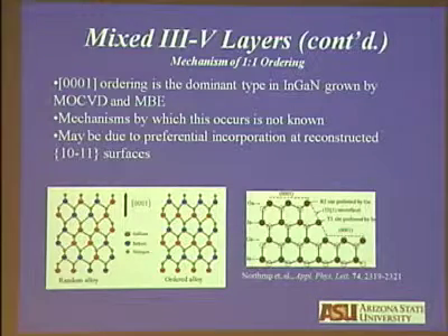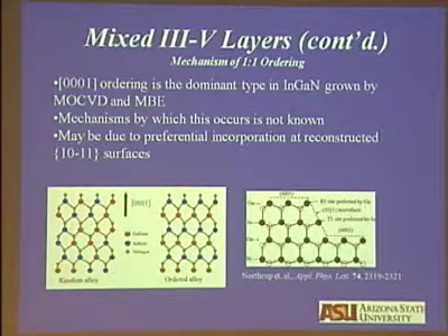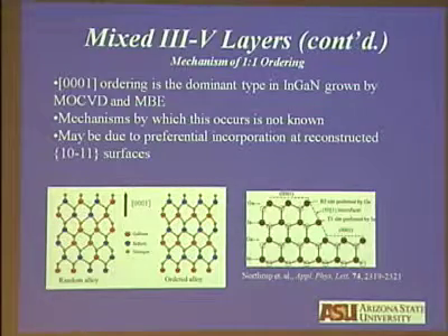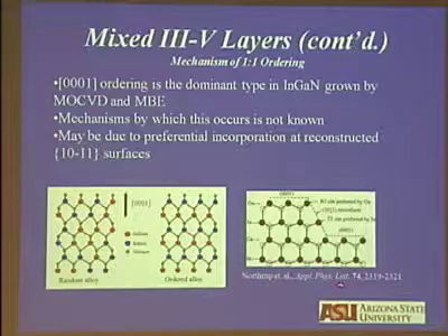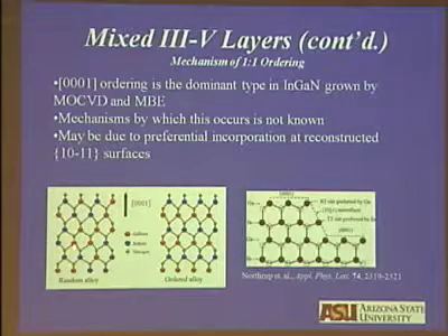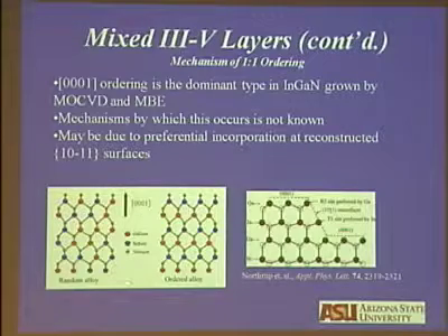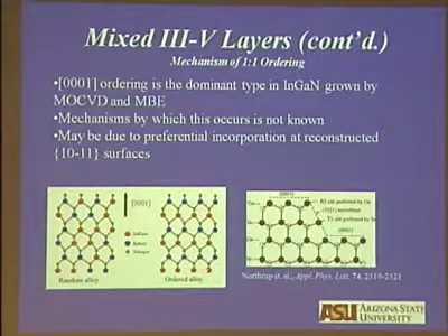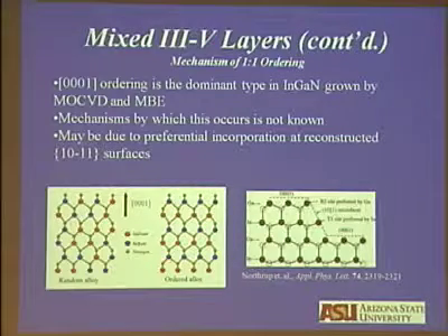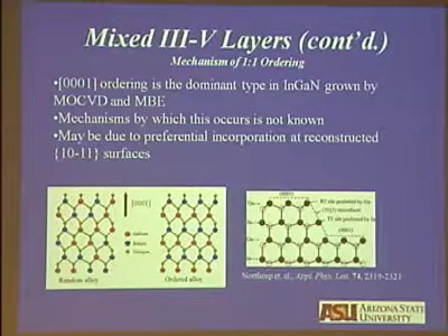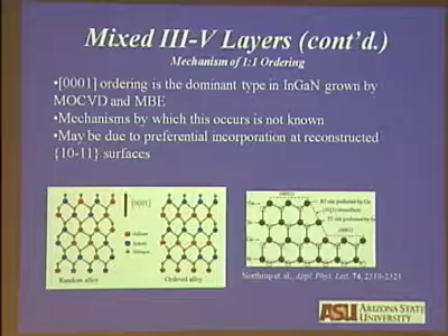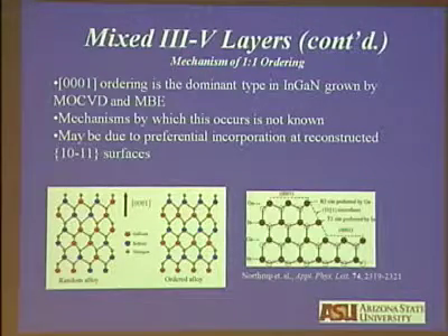Now, what's the mechanism? I will preface my remarks, we don't understand. And I'm going to speculate on the basis of the model Northrop developed. This is a plausible arrangement of atoms in a random alloy. What happens in the ordered alloy is you get gallium, nitrogen, indium, nitrogen, gallium, and the periodicity gets doubled.